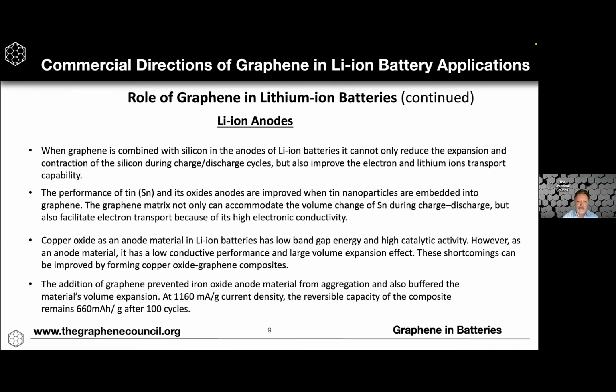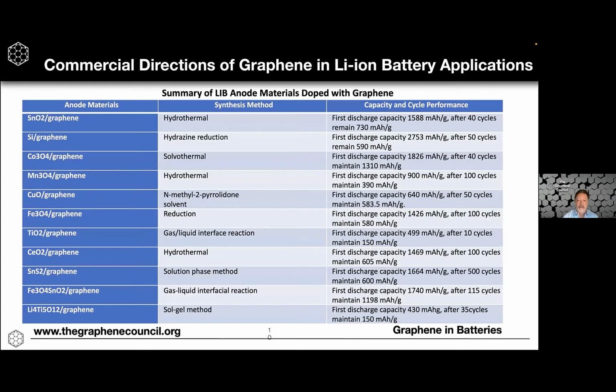I'll just go on to the next table here. This is taken as kind of an accumulation of a lot of different lab reports. So this table offers some interesting insights into the kind of trade-offs that occur with different battery chemistries. So you see silicon graphene obviously has the highest milliamp hours per gram at 2753, but it begins to fade dramatically down to 590 after just 50 cycles.